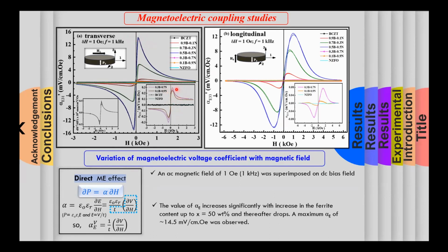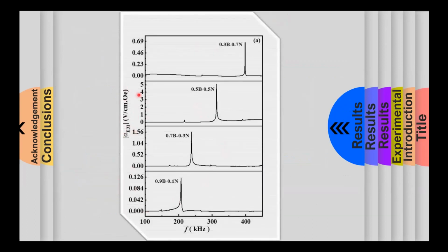While for higher concentration, both in transverse and in longitudinal mode, the response decreased drastically. And of course, the pure BCZT sample and the pure magnetic samples did not show any response because they don't have the two phases together. Here we see the variation of the magnetoelectric voltage coefficient as a function of frequency. Of course, it also shows the resonance behavior, and the frequency values were in excellent agreement with those electromechanical resonance that was obtained in the frequency dependence of capacitance and admittance.